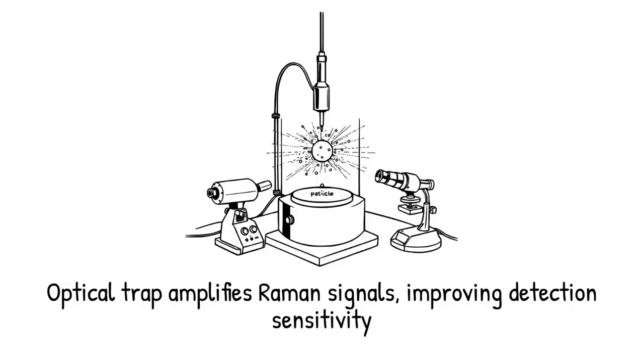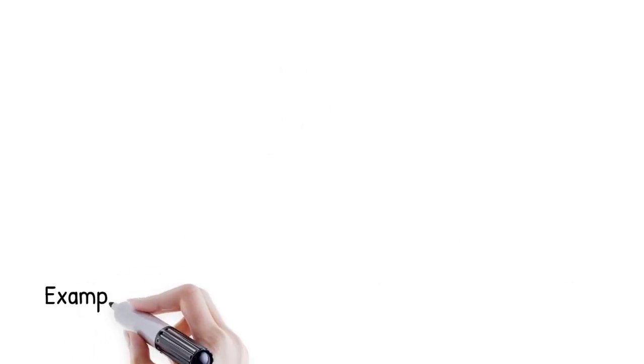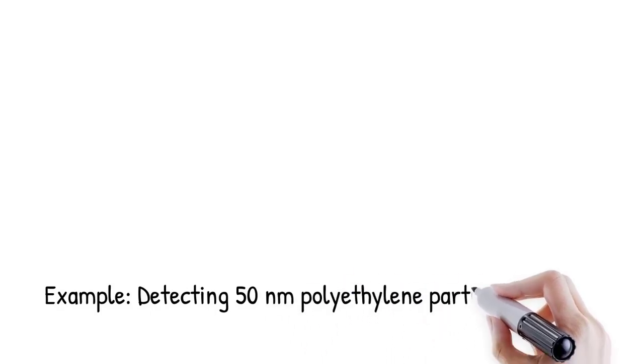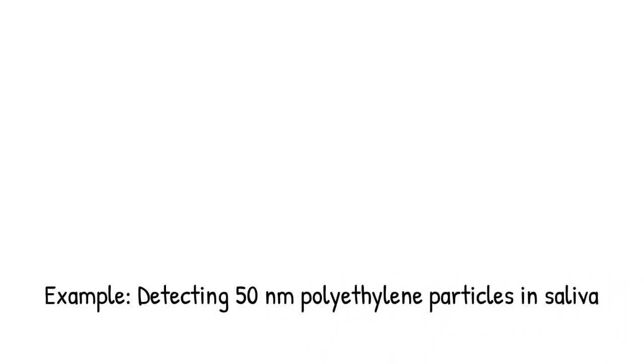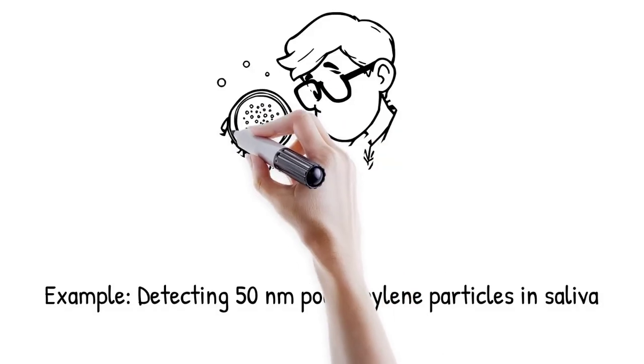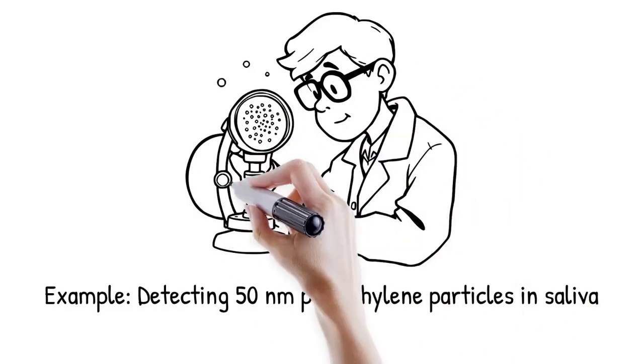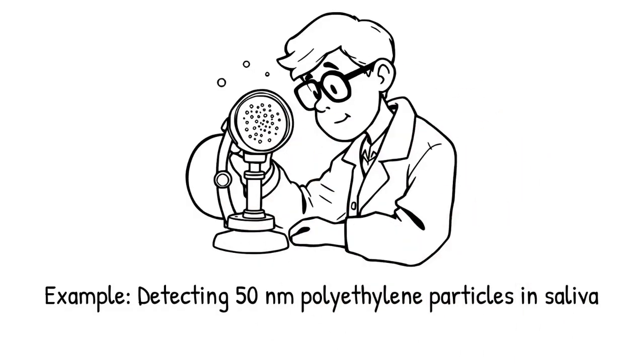This level of detection surpasses conventional centrifugation plus spectroscopy methods by 2 to 3 orders of magnitude. In simulated saliva, the method reliably detected 50 nm polyethylene particles at 5 particles/ml with over 95% confidence. It's like using a magnifying glass in a dark room to spot a single speck of dust glowing faintly.